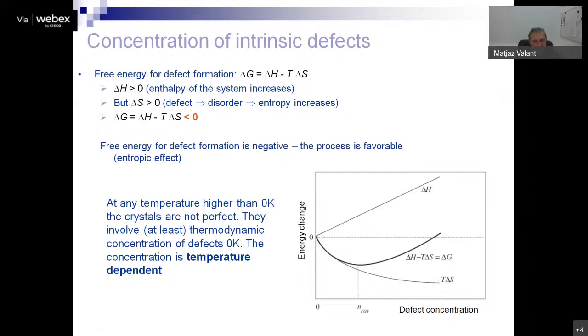Okay, now I will explain to you why you can't have an ideal perfect crystal. It's a very thermodynamically defined feature of the crystals. So we know how we write down the free energy of the system. Delta G is delta H minus temperature times delta S. Well, we have this enthalpy and entropy term here. So if we produce a defect in the crystal, that absolutely increases the enthalpy of the system, destabilizes it. And this is shown here. You see, the higher the defect concentration, the higher is the enthalpy of the system. This term destabilizes the crystal. However, we have also an entropic term here.